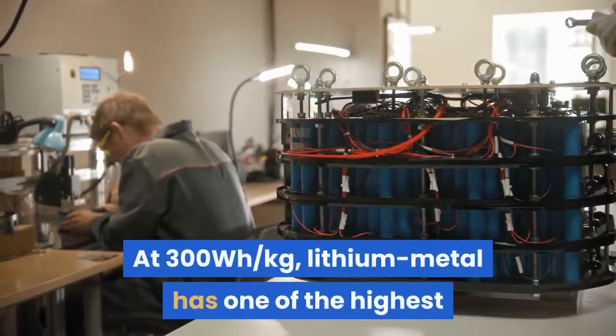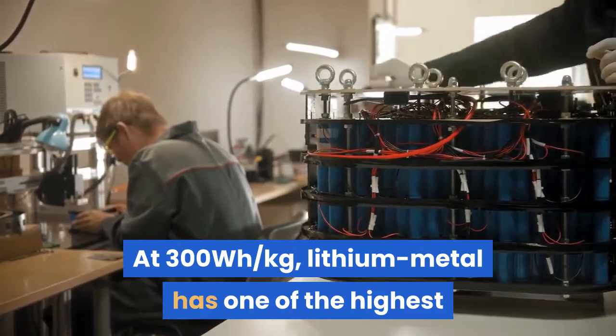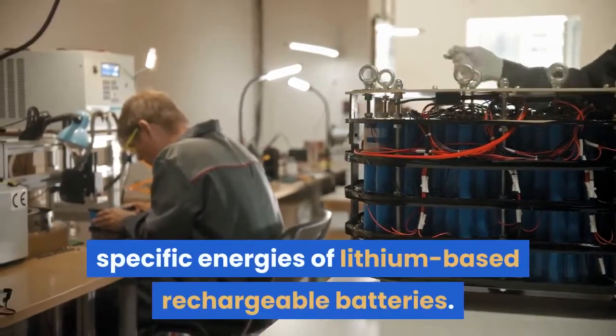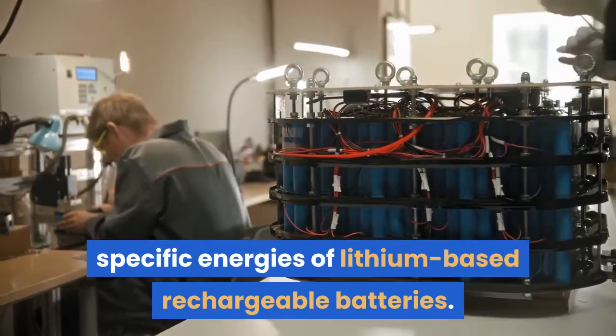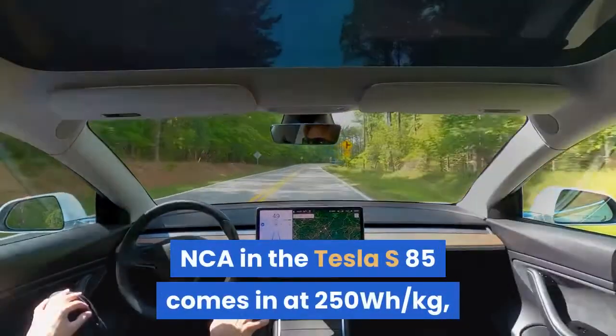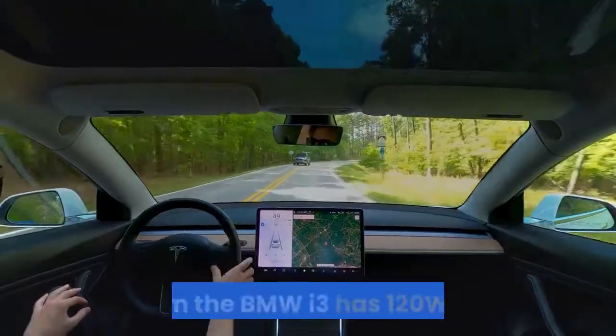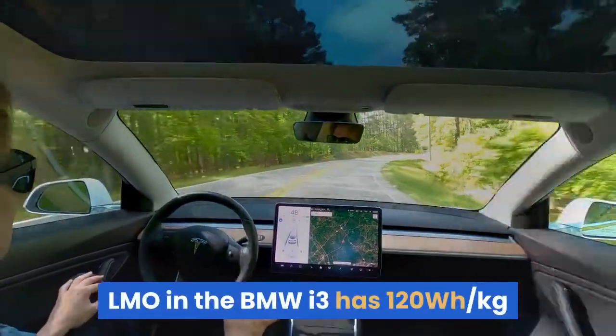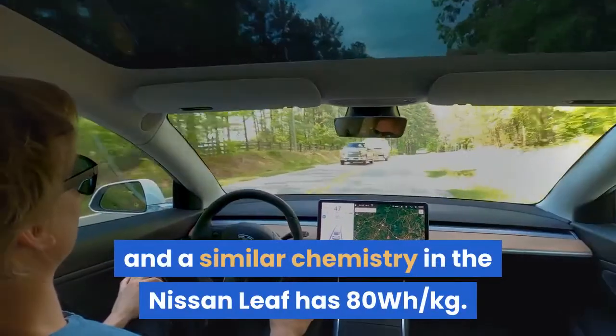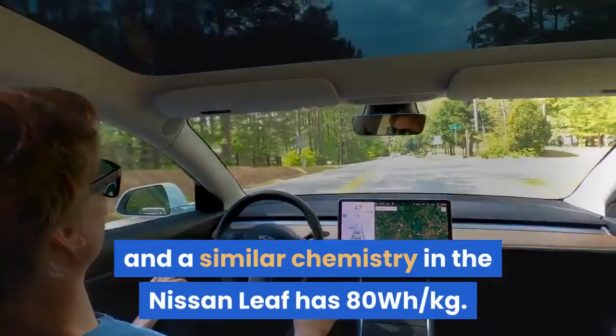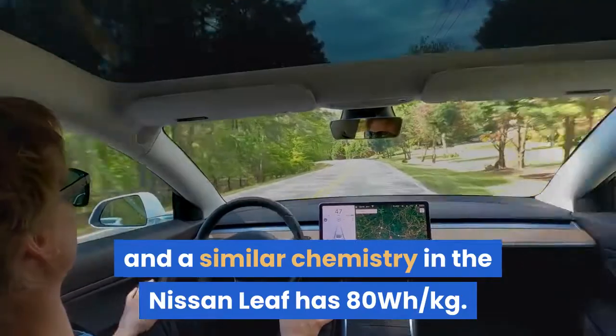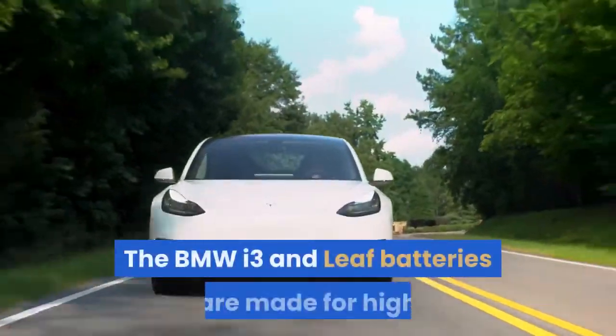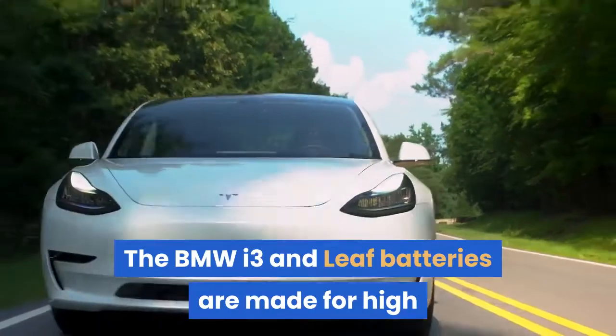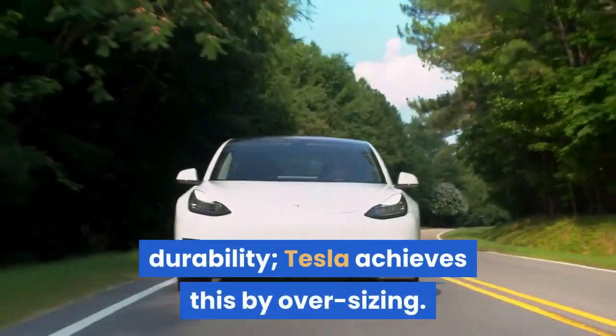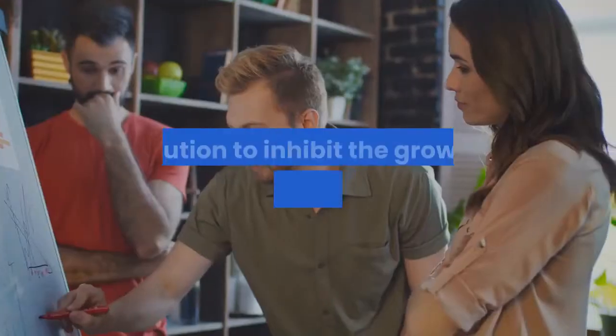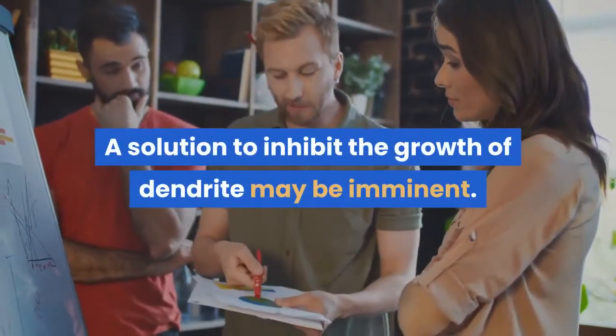At 300 watt-hours per kilogram, lithium metal has one of the highest specific energies of lithium-based rechargeable batteries. NCA in the Tesla S85 comes in at 250 watt-hours per kilogram. LMO in the BMW i3 has 120 watt-hours per kilogram and a similar chemistry in the Nissan Leaf has 80 watt-hours per kilogram. The BMW i3 and Leaf batteries are made for high durability. Tesla achieves this by oversizing. A solution to inhibit the growth of dendrites may be imminent.